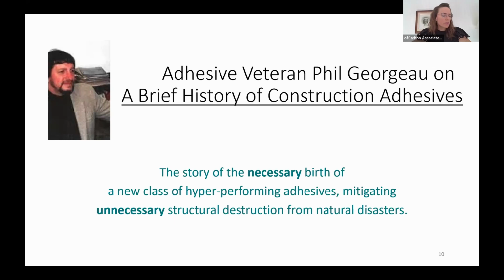Engineers at APA tried to expand the use of adhesives to walls and rafters with a MOD 24 program, meaning 2 feet off center versus 16 inches. They had good results, but this concept was not well received by spec writers because they could count nails, but a bonded glue line could not be verified. APA MOD 24 was therefore never implemented. There was also an embrittlement issue with that round of adhesive research, where they made it with urethanes, they made it very durable, but the substrate would fail, and therefore it wasn't adopted.